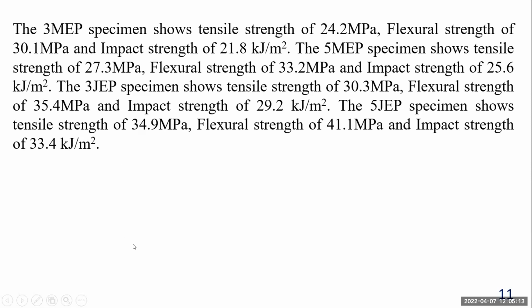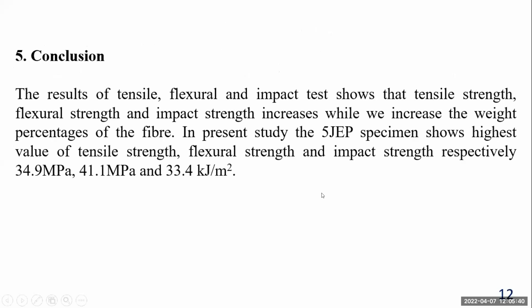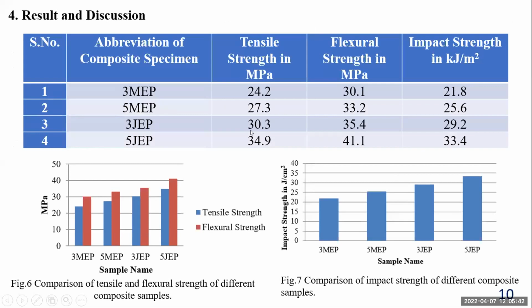The 3% jute epoxy composite shows a tensile strength of 30.3 megapascal, flexural strength of 35.4 megapascal, and impact strength of 29.2 kilojoule per meter square. And the 5% jute epoxy specimen shows a tensile strength of 34.9 megapascal, flexural strength of 41.1 megapascal, and impact strength of 33.4 kilojoule per meter square. These are also tabulated here.